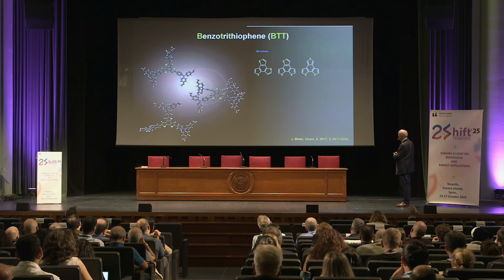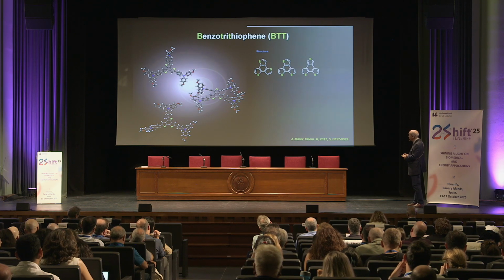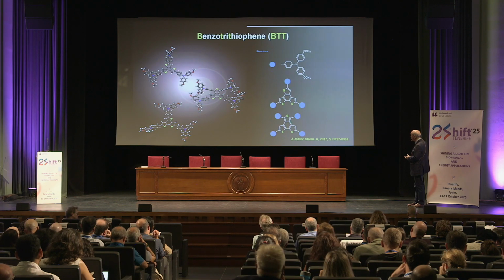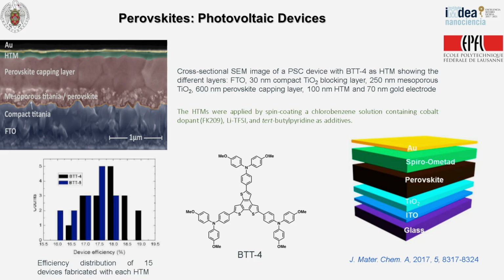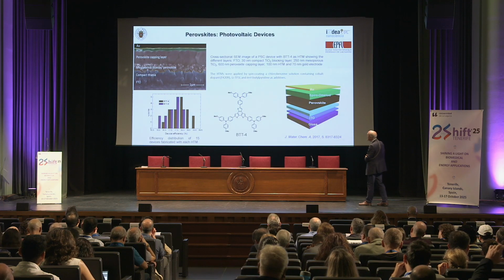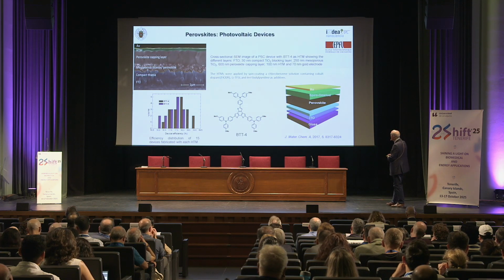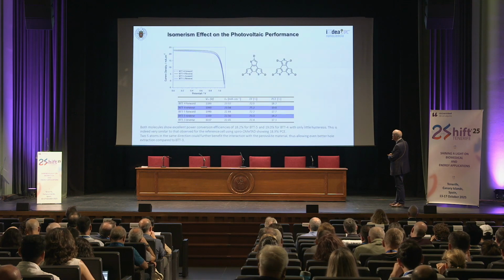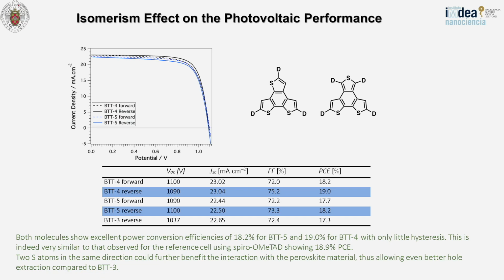So another possibility was to modify the position of the sulfur atoms. In this case, we did it by using triarylamines, and we carried out this study. You can see here the scanning electron microscopy, where you can determine the layers of the perovskite device and roughly see the size of the layers. In this case, this system resulted to be also of interest because the efficiency was also reaching 19%. The reasoning for this is that now the two sulfur atoms are pointing in the same direction, and this probably is interacting with the perovskite and therefore improving the quality of the interface.